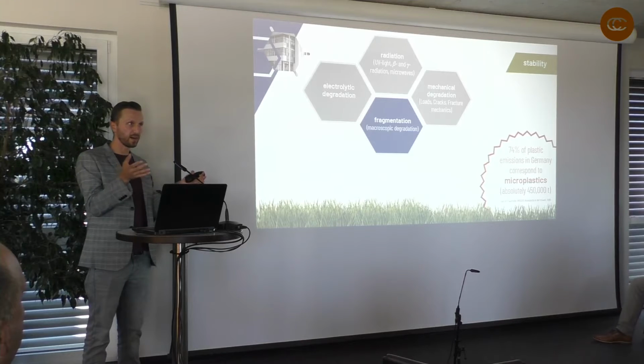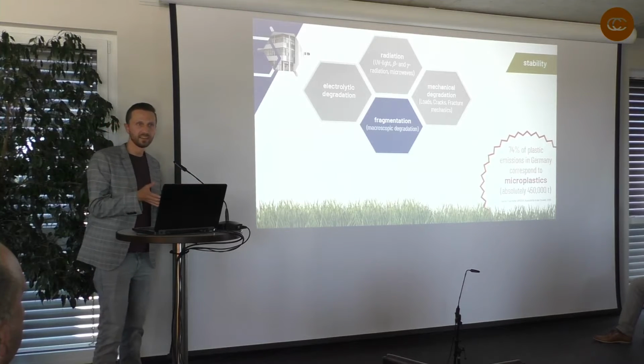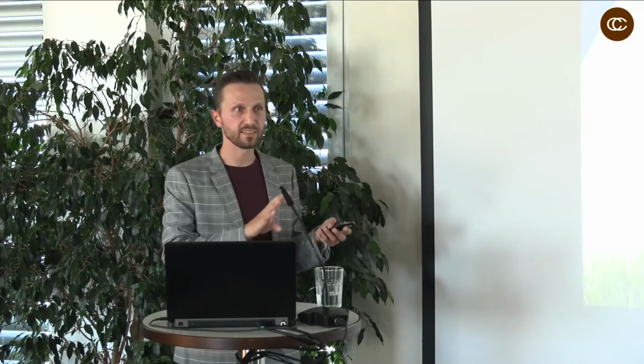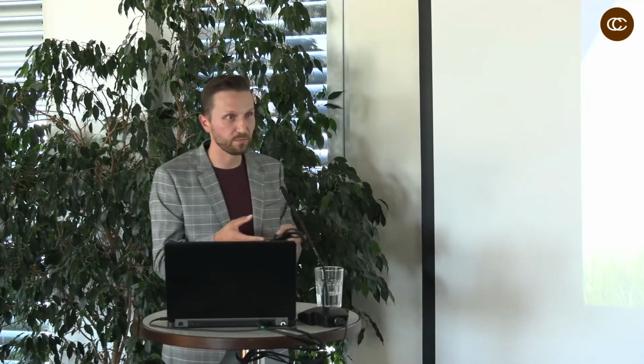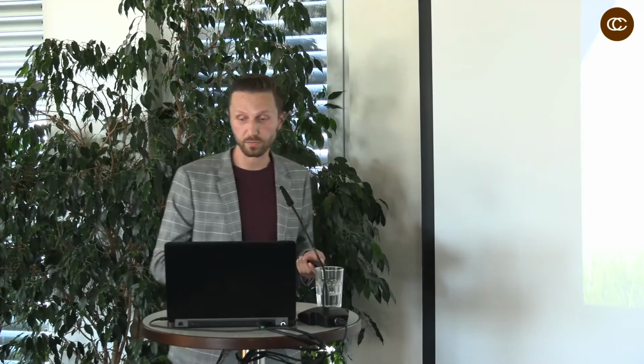I mean, think about how when you change your car tires, approximately every 2 or 3 years, after these 2 or 3 years, all your 4 tires have lost approximately 6 kilograms of rubber. Yeah? And the rubber is a polymer, and it's cross-linked, and this cross-link means that it actually cannot be biodegraded because of stable chemical bonds, and it's hardly possible to degrade it. Yeah? So think about this amount of microplastics, actually microelastics, because rubber is an elastomer.